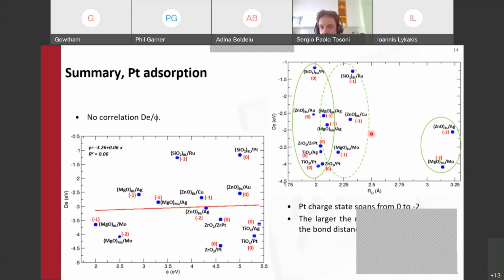The only way we found to group the data and derive some trends is represented here on the upper right panel. I'm basically grouping the adsorption energy of platinum as a function of the platinum-oxygen distance on the film. And as you can see, one can clearly identify three different groups.